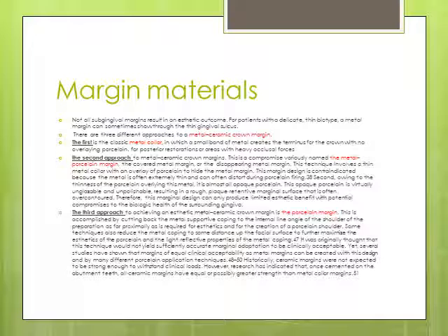At the same time, the thin section of metal will not provide enough support for the porcelain at this collar. Also, the metal may distort during sintering or firing of the porcelain on it because of the thin section. So it is not a good approach.